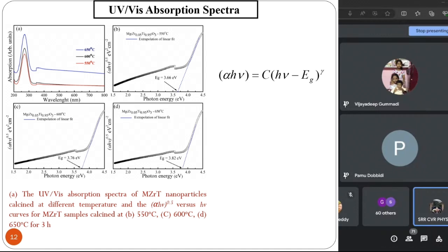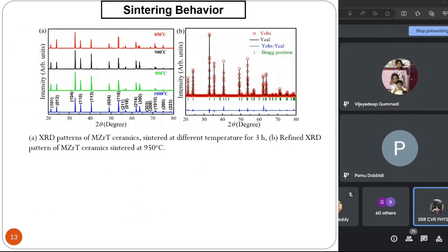See, we have also calculated the band gap. Generally, the reported band gap for this material is about 3.5 electron volts. But here you see that the band gap is increasing. Why? What is the reason? When you go to nanoparticles, quantum confinement comes into the picture because of the small particle size. As a result, the band gap is increasing. This is the reason for the increase in the band gap. Can you go to the next slide, please? That's okay. You go to the next slide.